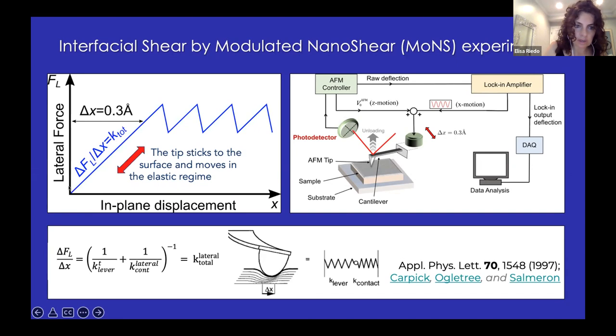This will give rise to our static friction and then our kinetic friction and the stick and slip. So in this part where we have just the contact, where you essentially just pull your contact, the change in lateral force divided by the change in displacement gives you the total effective stiffness, which is a stiffness given by two springs in series. One is the cantilever lateral spring constant, and the other one is really the stiffness of your tip substrate contact.